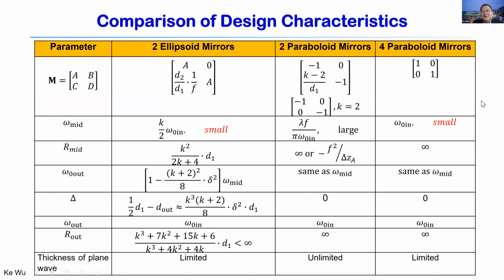So this is a comparison of the design characteristics of the different systems. We have ellipsoidal mirrors. As I said, the delta is a problem. You can see the value here. But the parabolic system actually gives you much better control of the beam for those specific spots on the material under test, and the thickness can be unlimited because of the beam, particularly the planar wave beam here. So that gives us advantages.